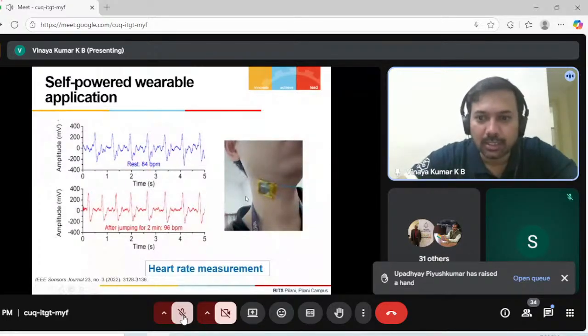Using the similar sensor, this is one of our students. We were able to measure the heart rate, like 84 beats per minute. Similarly, it is in a rest position. He's in the lab for like 1 hour, sitting doing his work, and he measured it. After jumping for 2 minutes, as you can see, of course, our heart rate will go up, right? So it reached 96 beats per minute, BPM.